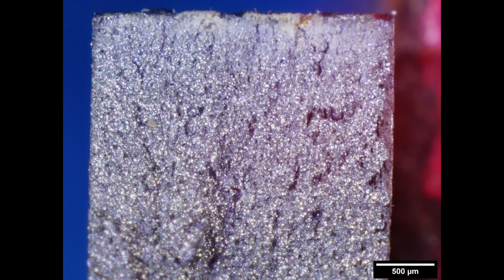during the quench. And then in the second set, we had the higher manganese. I also bumped up the austenitizing to 1475 for 10 minutes, which is more typical of what I do with simple high carbon steels. But even then, I was still getting a little bit of pearlite in it. You can see in this fracture surface of steel that I quenched in Parks 50, and this was only just barely over 2.5 millimeter, which is the final dimension for my toughness coupons. We could even see in the fracture surface these little black spots, which were the pearlite.